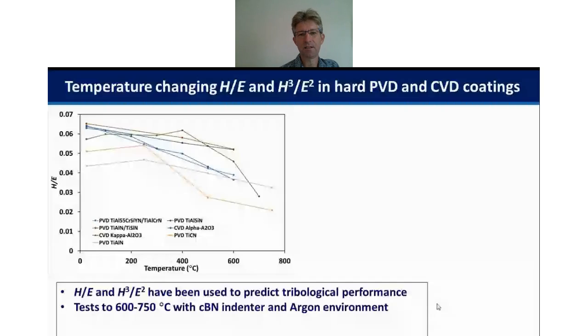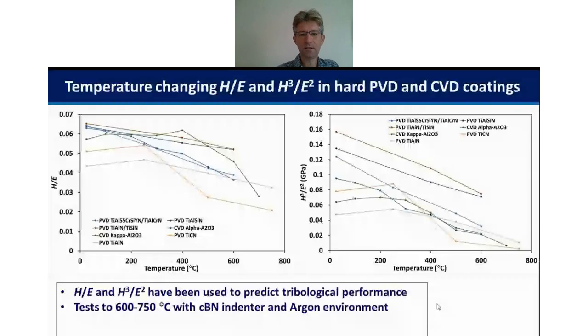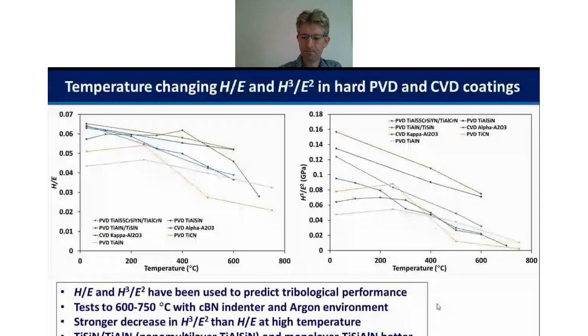The CBN indenter changes very slightly over that temperature range. And we can also see on the right that the parameter h cubed over e squared has a temperature dependency that is much stronger than h/e. So when we're using room temperature, we're saying it correlates with tool life. Actually, what we really need to be doing largely is looking at the high temperature behavior, and it's quite different at high temperature for this.